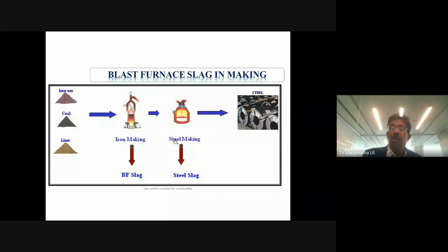Basically slag, you all know, you have a steel plant in Vizag, blast furnace slag. How is it manufactured? It comes from the blast furnace. We have iron ore, coal, and lime, all fed as flux into the blast furnace. Here it is heated up to 1500 degrees centigrade. Then we get high quality iron. Almost 30% we get as slag. It's called blast furnace slag. Blast furnace slag is rich in calcium silica aluminates. So it has a very good product mix: calcium oxide is there, silica is there, alumina is there. That's the reason it is very good as a cementitious material.